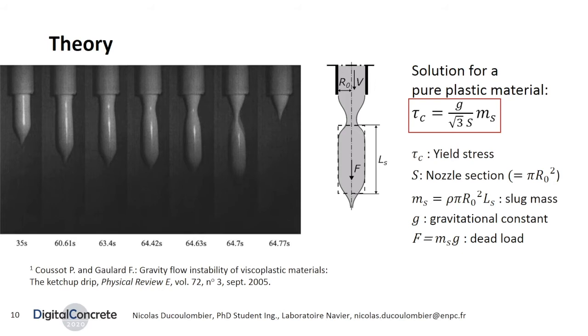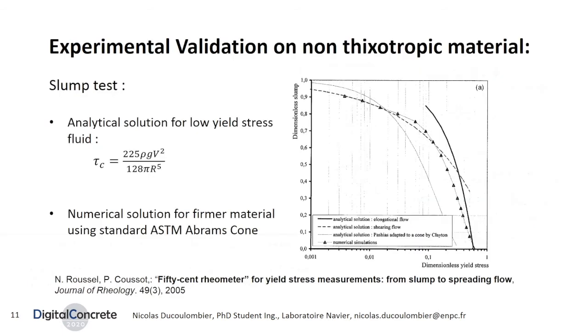This equality is the fundamental relation of the slug test, where the right-hand term is simply the expression of the direct traction von Mises stress at the nozzle exit under self-weight, which only depends on gravitational constant g and the nozzle cross-section S. The experimental validation is then conducted on non-thixotropic material. As a consequence, the yield stress measured by the slug test can be compared with the yield stress given by